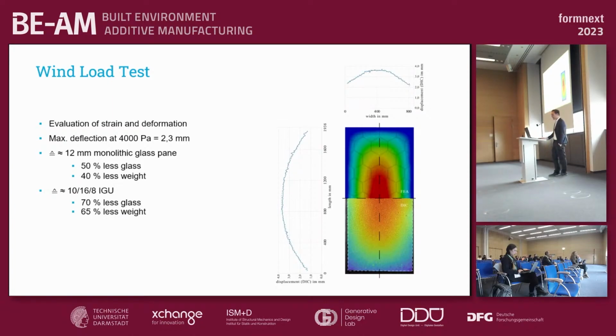Another example to compare it with is an IGU, an insulating glass unit that is probably more common, like you see here in the facade as well. There you have a 10 millimeter glass sheet outside, a 16 millimeter cavity filled with air or a different gas, and an 8 millimeter glass sheet on the inner side, and that would mean already 70% less glass and 65% less weight.